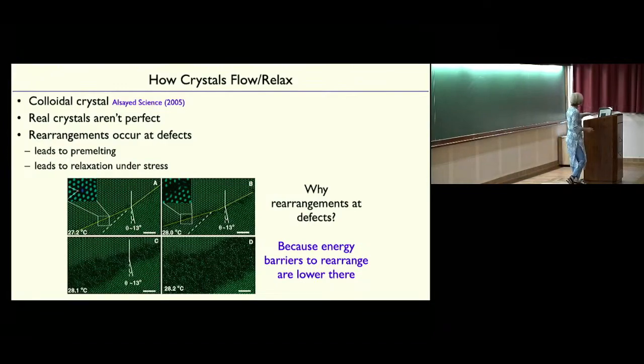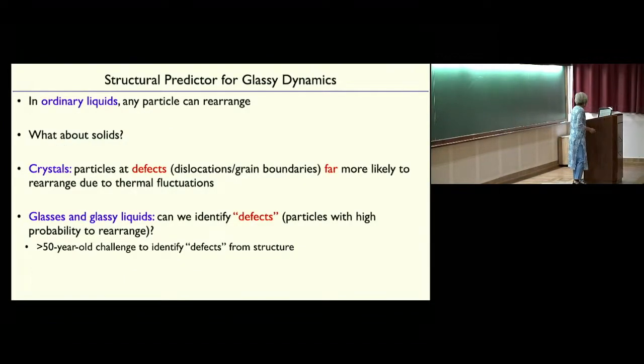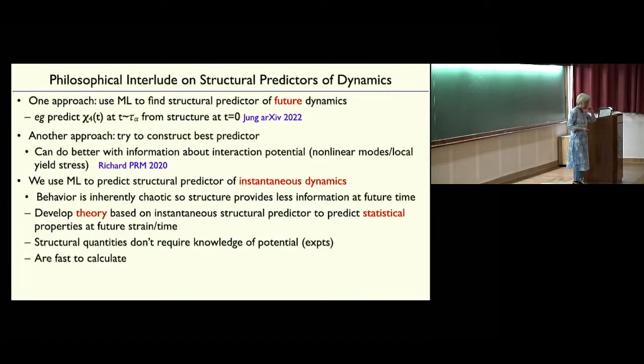So that was the challenge. Can we define these defects which have lower energy barriers that allow them to rearrange? And of course, the point is that we can, with machine learning. Now, before I go into this, I'm going to take a moment for philosophical reflections, which is that what we're doing is using machine learning to find a structural predictor of whether the particle is going to rearrange now, right away.